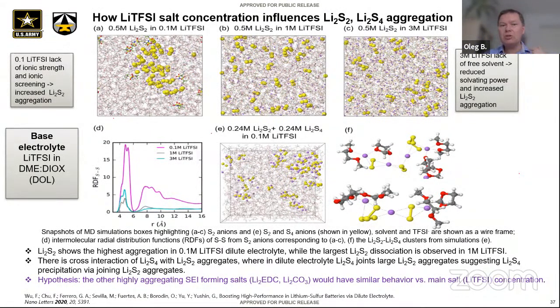I can describe accurately the Li2S2, Li2S4 and Li2S binding energies with just a polarizable force field and a Buckingham potential. So I don't need covalency to describe them systematically. That also gets me accurate structures of Li2S. I was surprised at how well the force field does from that perspective without any covalency. I think the reason people talk a lot about covalency is that you need it when you break the sulfur-sulfur bond. For that, Adri van Duin had a reactive force field, which I'm not doing. I'm just describing the lithium-sulfur interaction if the sulfur bond doesn't break. That can be done with a polarizable force field pretty accurately, I think. Okay, thank you.